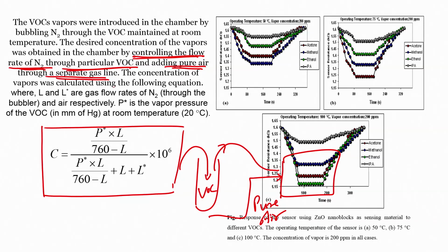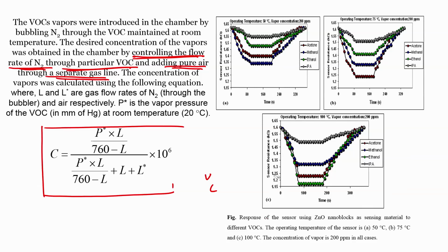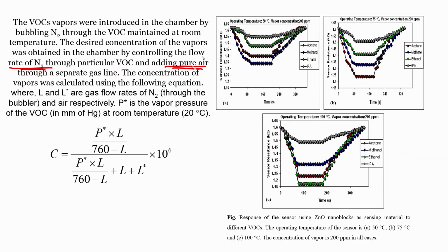The concentration of vapors was calculated using the following equation, which is C equals P star into L divided by 760 minus L, whole division by P star into L by 760 minus L plus L star, into 10 to the power 6. Now, you see here, L and L star are the flow rates of gas, nitrogen through the bubbler and air respectively, while P star is the vapor pressure of the VOC measured in millimeter of Hg at room temperature.